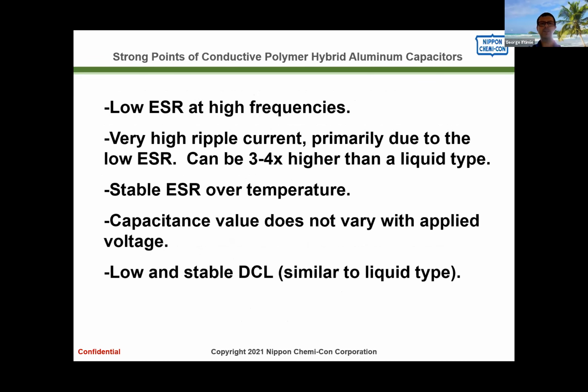The advantages of the hybrids: they have a very low ESR at high frequencies, not quite as low as full polymers, but very close. They have a very high ripple current also because of the low ESR. They also tend to have a very stable ESR over temperature, same as the polymers. The polymer material is what actually drives or controls ESR. But because they have the liquid electrolyte also, they will have a capacitance change over temperature. Of course, the capacitance does not change with the applied voltage, and they also have a low and stable DCL. Not quite as low as a liquid capacitor, but very low, and much lower than a polymer capacitor.